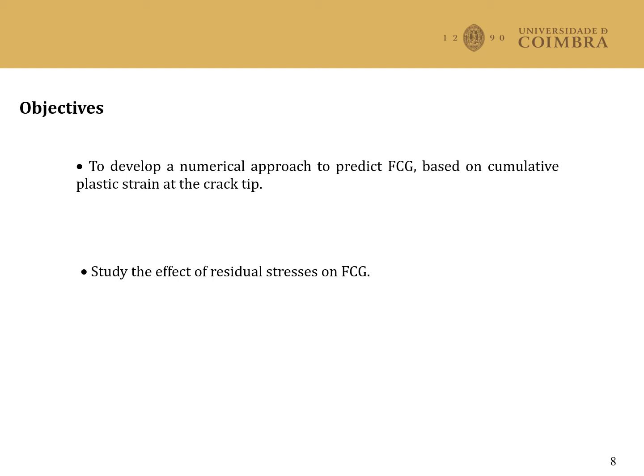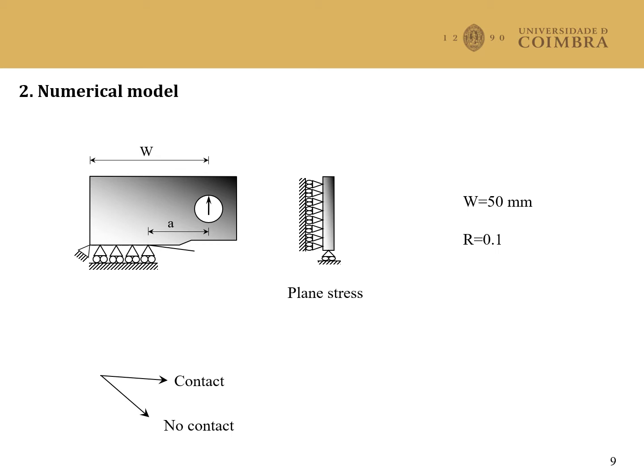A CT specimen with a width of 50 mm was considered in this study. Only one-fourth of the specimen was modeled, considering adequate boundary conditions. A pure plane stress state was considered. The simulations were made with rigid contact of crack flanks, which is very interesting to isolate the effect of crack closure and is only possible in numerical work, being impossible in experimental work.